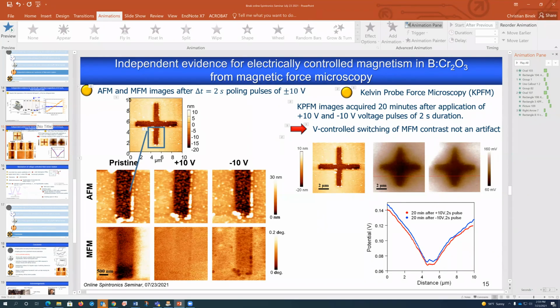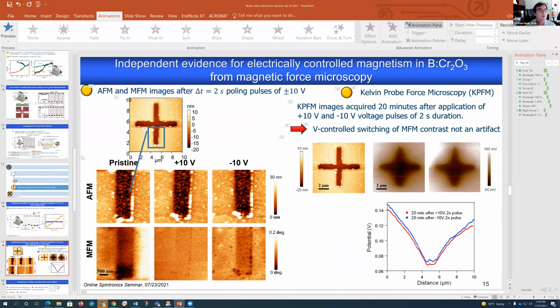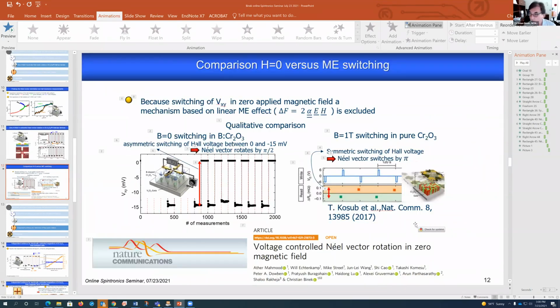Thank you very much. When you mention 180-degree rotation of antiferromagnetic order, do you mean 90-degree rotation or 180-degree rotation of the magnetoelectric effect, or 180-degree rotation of interfacial uncompensated moments? Okay. I hope that wasn't too confusing. Let me come back to this. I talked about both. The point being that in pure chromia, the textbook archetypical magnetoelectric material, if you apply an electric and a magnetic field to that system and you overcome the critical value, you indeed switch the order parameter by 180 degrees.